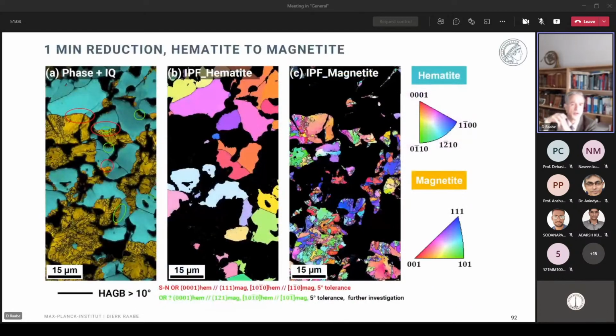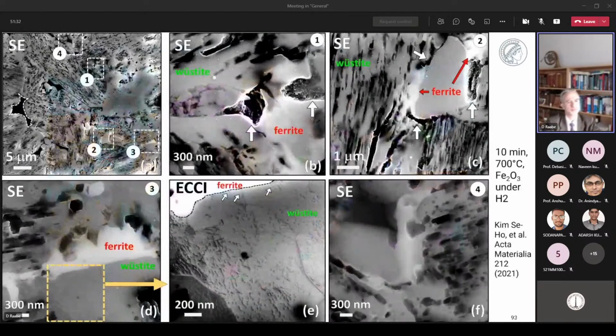Why? Here you see on this picture, after 1 minute at 700 degrees centigrade, the light blue is the hematite with the relatively big grains, and the orange ones, which are much finer, are actually the freshly formed magnetite. And as you see, they are not so terribly coherent. They have some plane match planes, but others do not match. So you have a relatively classical nucleation and growth type of problem.